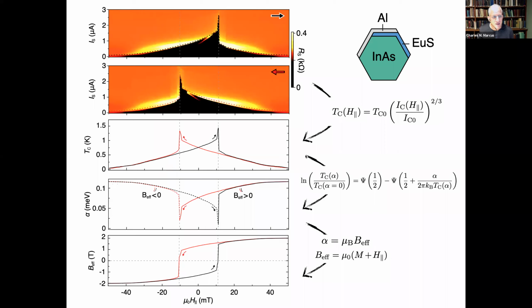You can then go from the critical temperature through this Abrikosov-Gorkov mean field theory, which you may or may not like, but this is a good way to go from the critical temperature to what's called the pair breaking parameter, alpha. And alpha has this feature. And if you then say that the alpha, the pair breaking in the superconductor, can be attributed to an effective magnetic field, as if it were a pure Zeeman field, then you can just infer what was the effective magnetic field that was causing this structure in the critical current to begin with. And it doesn't have any parameters, because the alpha that you get is the alpha that tells you what the critical magnetic field is. All you have to use is the zero field critical temperature, which we also knew, and that tells you everything that you need to know.